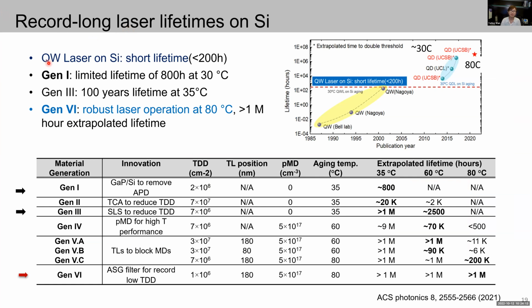Remember, the maximal lifetime of quantum well lasers grown on silicon is only 200 hours after several decades of research and development. Our generation 1 quantum dot devices already show a lifetime of 800 hours at 30 degrees C, and later 100 years of lifetime at 35 degrees C. And our most recent results show a remarkable improvement of 1 million-hour extrapolated lifetime at 80 degrees C. This is much better than our first generation of devices, and also orders of magnitude better than any kind of quantum well lasers grown on a silicon substrate.